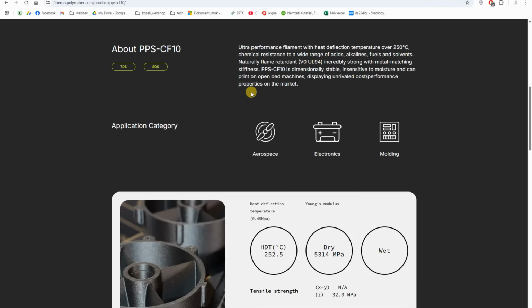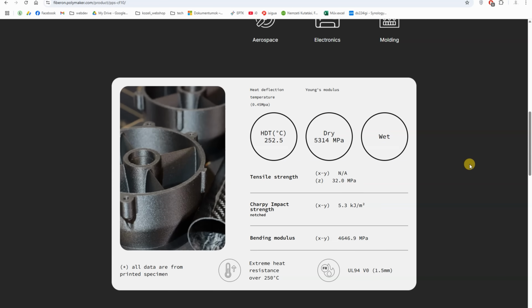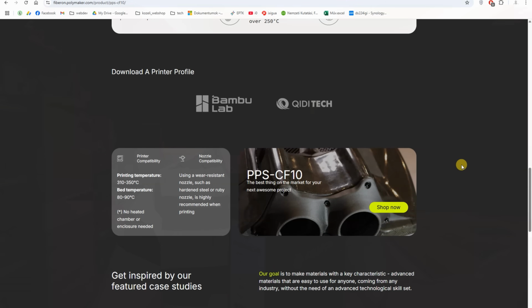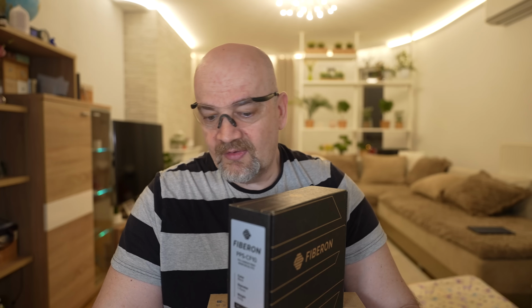Let's see a few specifications from the website. Heat deflection temperature over 250 degrees Celsius, chemical resistant filament, high mechanical strength, naturally flame retardant, insensitive to moisture. Looking at the specifications, it is better than PPA-CF, which I recently tested on this channel, several brands.